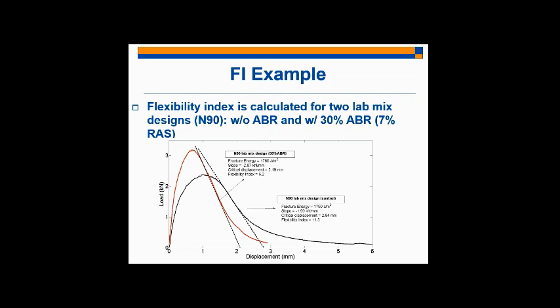between the two mixtures. So the red curve, or the more brittle curve, or we can agree the lower performing curve in terms of low temperature fracture resistance, displays a flexibility index value of 6.2. Whereas the black curve, or the softer, more ductile curve, of the lab mix with 0% RAS displays a flexibility index of 11.3 for its fracture performance. So you can see that the black curve is displaying a significantly higher flexibility index than the red curve. And so the distinction is then made. So these two mixtures are distinguished using the flexibility index, which was not done before using the fracture energy.